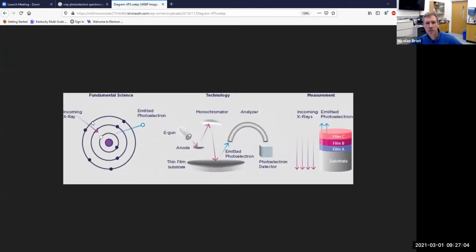So here's the idea about XPS. Again, you send X-rays. That X-ray is going to knock an electron out of the atom. So it's called a photoelectron because it's a photon that created that electron. And again, this has such a low energy that only the one close to the surface can be captured. So if you see on the right here, if you have a substrate and several films, for example, the X-rays are going to penetrate very deep, as I was saying, but only the photoelectrons close to the surface are going to be able to travel. So you might not be able to see film B or A, depending on the thicknesses, and you're not going to be able to see the substrate. So that's very interesting here.